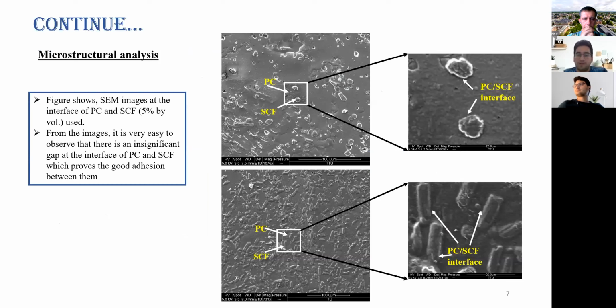Now, microstructure analysis. I told you that we generally use two different materials for increasing the properties of the final part, right? But the question is, which two materials? Why do we use polycarbonate and short carbon fibers? Why do you choose those particular two materials? We have to check whether the two materials we chose are compatible with each other or not. It's not that we can choose any two different materials, just mix them, do the 3D printing and create any structure. You have to check whether they are making good bonds with each other, because bonding between any two materials is very important to ultimately increase the final properties, right?